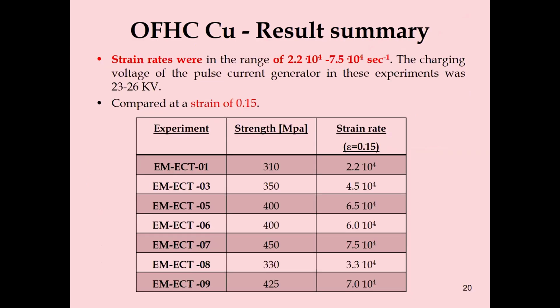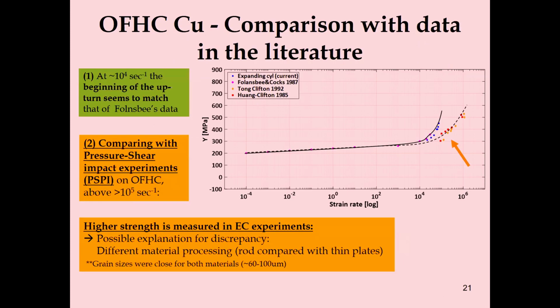So these are the results we got for copper. We were examining the range of just over 2 times 10 to the 4. We were trying to reach 10 to the 5, but at the end of the series, we reached up to 7.5 times 10 to the 4. And we were reaching from around 310 megapascals to 450. If we compare that to the literature, the results of this research are the blue dots over here. So we're comparing first to the results of Follansbee and Cox, and you could see first that the upturn is predicting something similar to what they were showing. They were showing just the onset of this upturn.